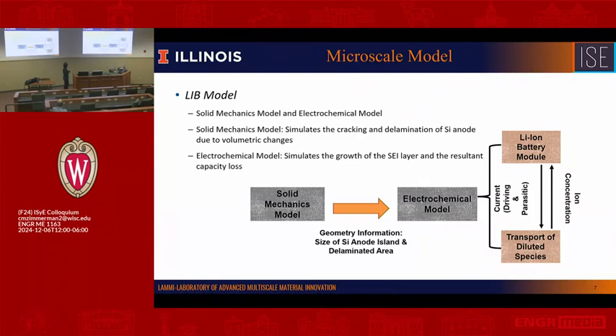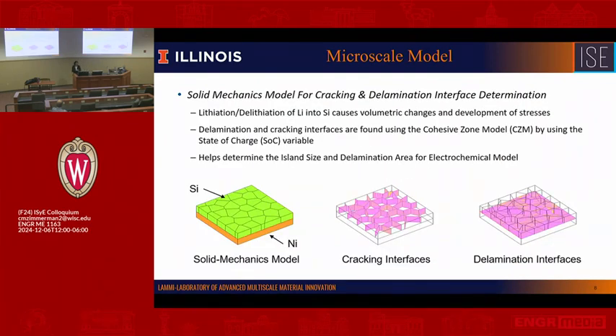So at the micro scale model, we also have two models. Right now it's one-way coupling. We have the solid mechanics model for capturing the cracking and delamination. With that quantified, we can pass that to the electrochemical model to quantify the electrochemical degradation, mainly due to the formation of the SEI layer. The SEI layer is one of the dominating failure mechanisms that can consume the electrolyte and also increase the resistance of the electrode, which can change the transportation of the ions within the electrodes. That's the major mechanism we want captured in our electrochemistry model, and use that to quantify the performance of the battery.